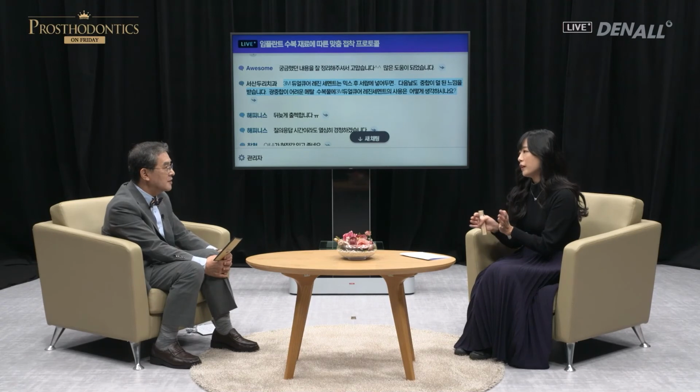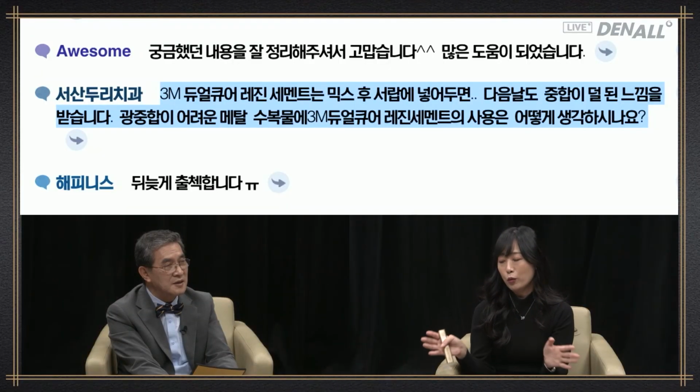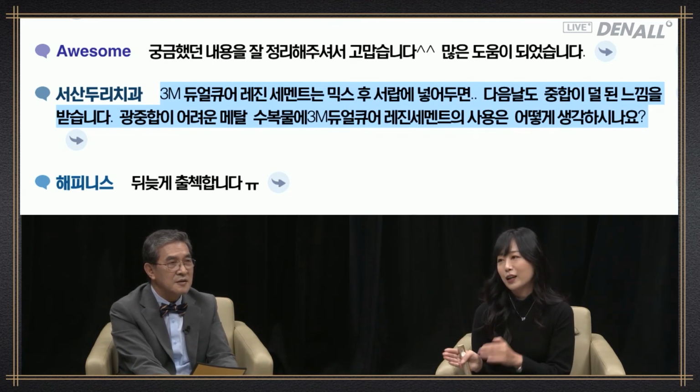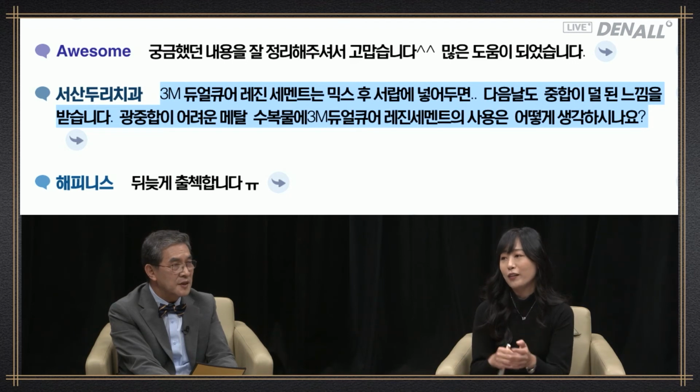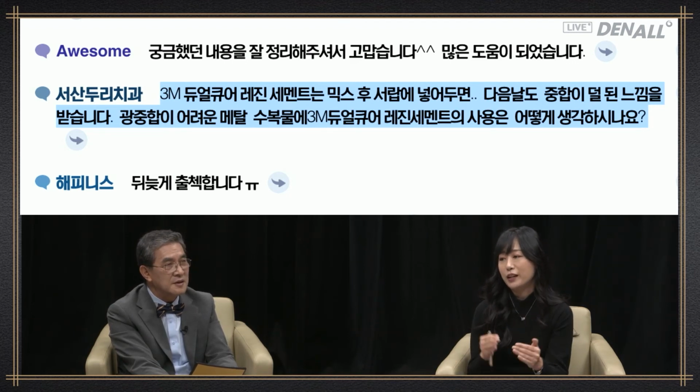However, light curing needs to be included. Light curing leads to better cementation strength, even if it is metal. You do tack cure on the marginal area, seal the marginal area, and remove excess cement. And finally, you need to do as much light curing as possible. In the case of metal restoration, you need to do light curing to increase cementation strength.